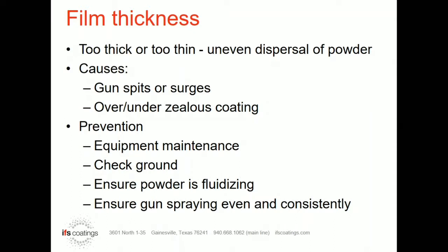So like I said earlier, if you do not put enough powder on there, you're going to see a very thin, rough looking result. Depending on the color, you will even see the substrate show through and have a wrong color, especially yellows, reds, oranges. They don't hide well in the first place. So if you're a little low on film build, you could potentially see a color issue with that.